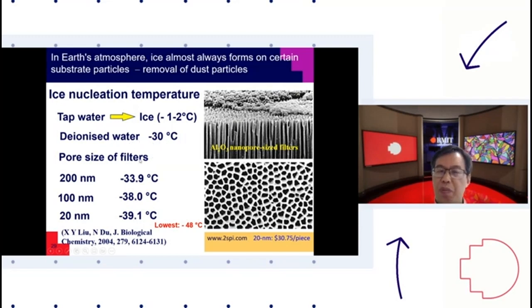However, if we let the deionized water run through filters with a size of 200 nanometers, that would further reduce the ice crystallization temperature. If we let this water further run through filters of 100 nanometers, the ice crystallization temperature becomes lower again. And the lowest temperature that has been reached by scientists is -48. So by letting the water run through the filters, we have removed all the fine particles.